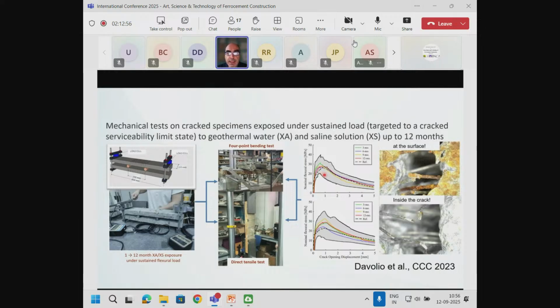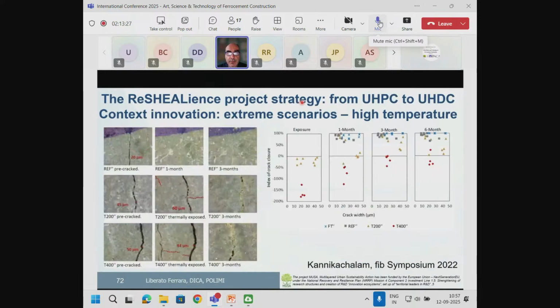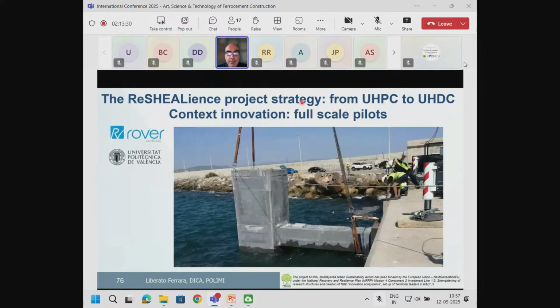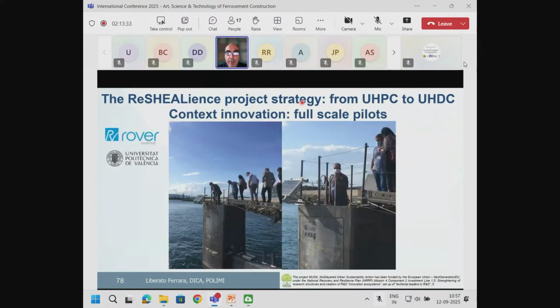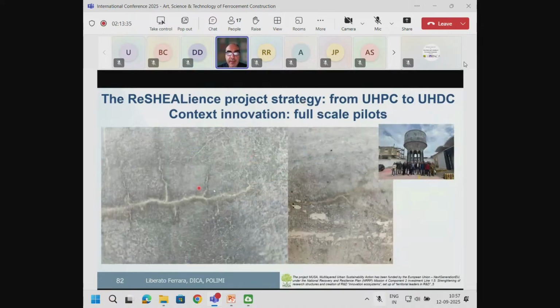So up to 1 year, if you see this gray one is the envelope of the test at time 0, let's say, and the colored curves are the tests performed after 3, 6, 9 months, up to 1 year. So the material did not exhibit any degradation. And also, if you look at these pictures here, these cracks are at the surface, so you can see that there is some rust. But if you go inside, there was no corrosion. So as a matter of fact, you can see here some images that I showed you. For example, this one here, we had cracks, but they were completely closed. Some images are here.